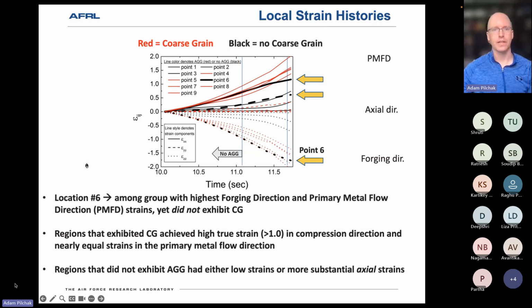We took a look initially at the local strain histories: the principal strain components along the primary metal flow direction, which we're calling PMFD, the axial direction, which is the strain along the original bar axis, and the forging direction, which is obviously the primary compression axis. From this plot, you can see a couple of interesting things. A side pressing operation is akin to plane strain compression, so it's not surprising that we see primarily strains along the primary metal flow direction and the forging direction, and relatively little movement in the axial direction.